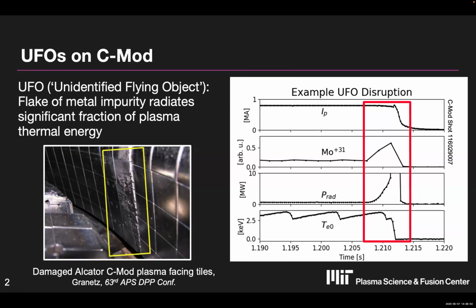So what does this look like if you're operating a machine? Here's an example of a time trace from an experiment on Alcator CMOD, our old tokamak at MIT. In the top panel, we have the plasma current. That's nice and steady, around 1 megaamp. And we're about 1.2 seconds into the plasma pulse. In CMOD, a typical plasma pulse would be 2 seconds. The second panel is the molybdenum content in the core of the plasma, so that's nice and steady, which is good. We want that to be low.